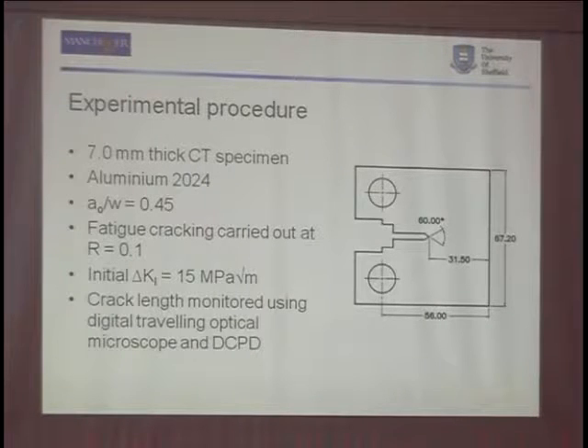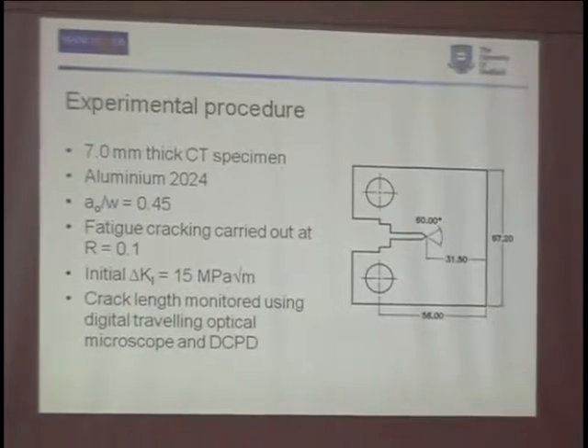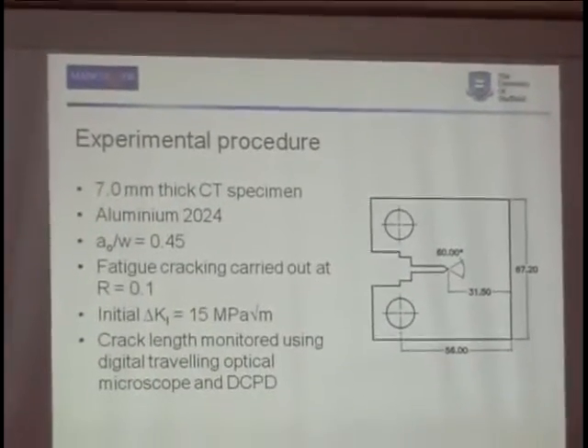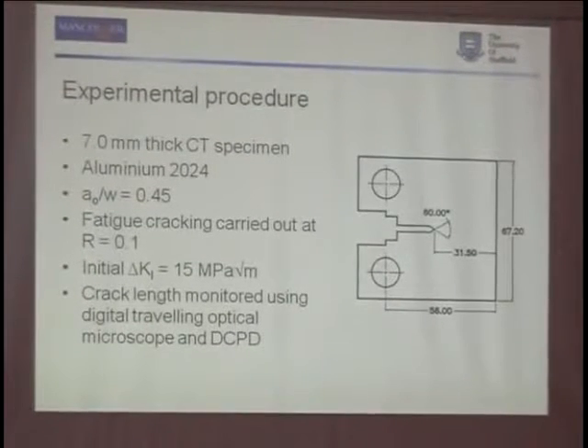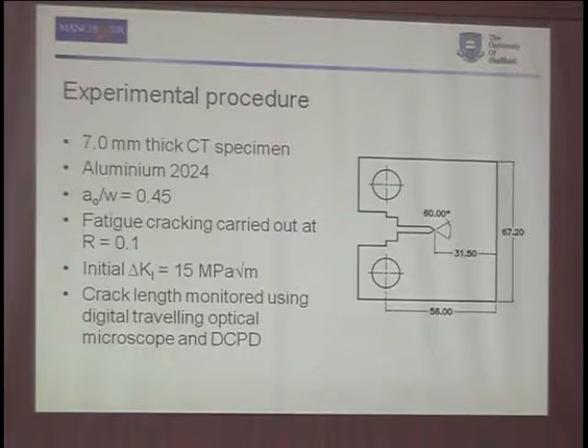This was a 7mm thick CT specimen in 2024 aluminium. The grain size was fairly large, so the fatigue crack wasn't as straight as we liked, as I'll show you later. The initial a/W was 0.45. Fatigue cracking was carried out at an R ratio of 0.1. As opposed to load shedding, or reducing the load as the crack grew, we just started off with an initial delta K of 15, which was about 2.5 kilonewtons. And we pre-cracked this specimen up to a 5.3mm crack, and then we just tore it to get some tearing crack data.